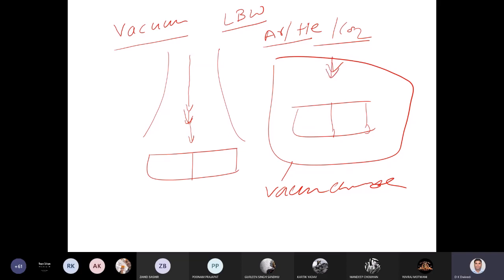Now you direct the electron beam. The air has been removed from the vacuum chamber and the electron beam is directed onto the base metal for melting. Because of the high power density, it melts and produces a very high quality joint, because heat delivery is very less for facilitating the fusion, as well as vacuum is created so that there is no presence of oxygen and nitrogen to degrade the quality of the weld. So this is the third approach of protecting the weld pool.